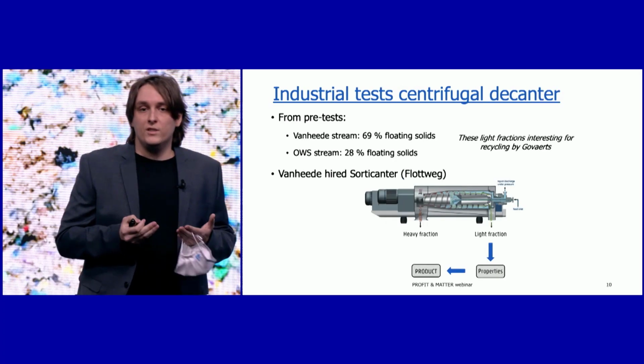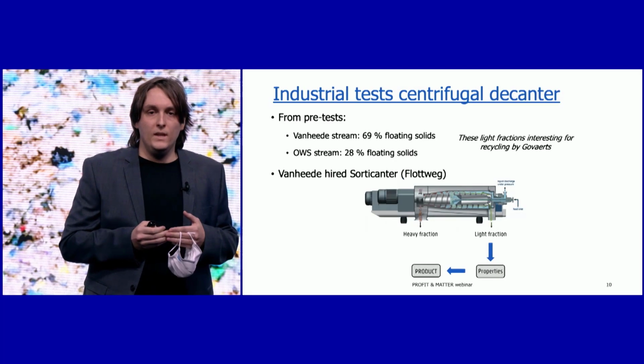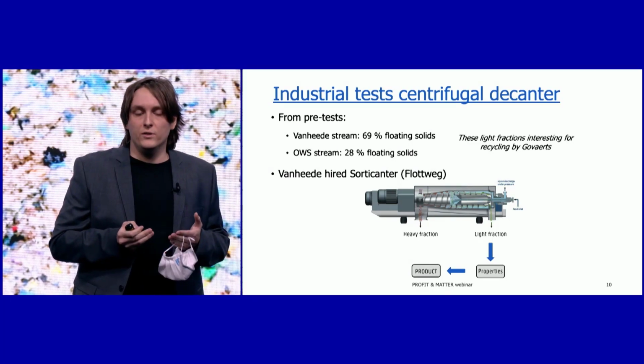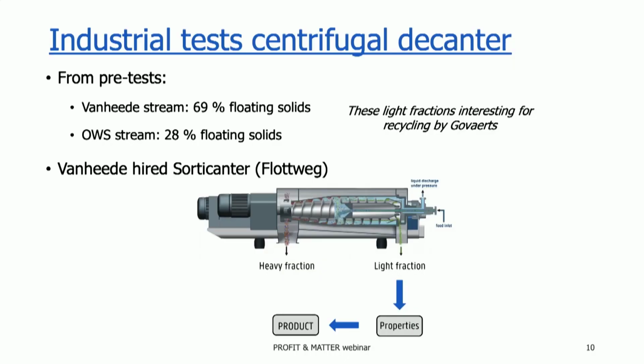Also on an industrial scale, we did some tests, and therefore we hired a centrifugal decanter. With this machine, we were able to separate the heavy and light fraction of both waste streams into two dry fractions, one heavy and one light. The plastics of Vanheede and OWS are showing promising floating solids, and those light fractions can be recycled at Govaerts.